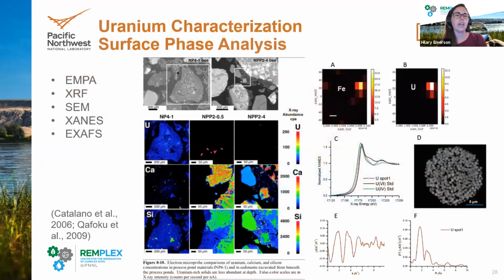And so here I have an example on the left of a map constructed with an electron microprobe. And this is a great surface sensitive technique for looking at morphology and also the elements with which uranium is associated. And then on the right at the top in A and B, we have a micro X-ray fluorescence map that shows a particle with uranium and iron co-associated. And then in D, we have another great surface phase technique known as scanning electron microscopy.